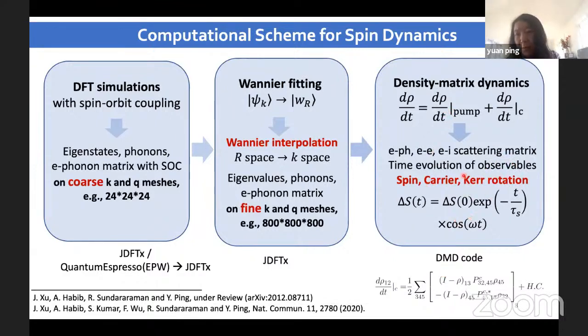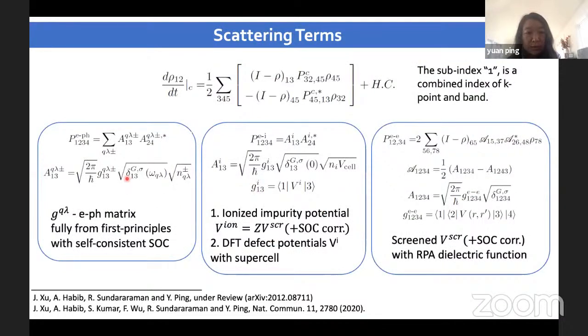The most time-consuming part is how to compute the scattering. There, as I show here, for each part, we deal with it from first principles with a certain level of approximation. For the electron-phonon part, it's rather established. We include also self-consistency. For the electron-impurity, we treat the ionized impurity with a screened Coulomb potential, which deals with the long-range part more correctly. And for the neutral defect, we use the supercell DFT potential. For electron-electron interaction, we include the screened Coulomb potential with RPA dielectric function. We benchmark against the GW self-energy at finite temperature.